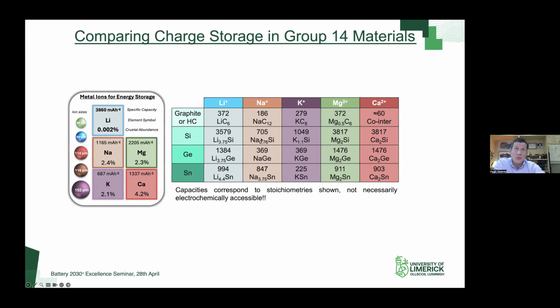But it is extremely challenging to form that electrochemically in the first place. So what you can think of this is almost as a roadmap where we would try and access some of these higher capacities. So for example, up here in the case of magnesium, if we could form this magnesium 2 silicon alloy here, you could boast really, really high capacities here. So this would be up around 3,817 milliamp hours per gram.